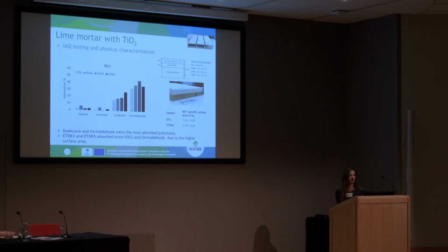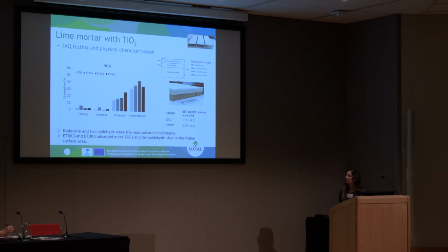This is a study that I did with the materials prepared by my colleague Andrea Gianpiccolo. So this is a lime mortar prepared with titanium dioxide. And I observed that by increasing the content of titanium dioxide, the uptake of VOCs increased as well. So then I studied the surface area by BET, and it proved that the higher the surface area, the higher the amount of VOCs absorbed.